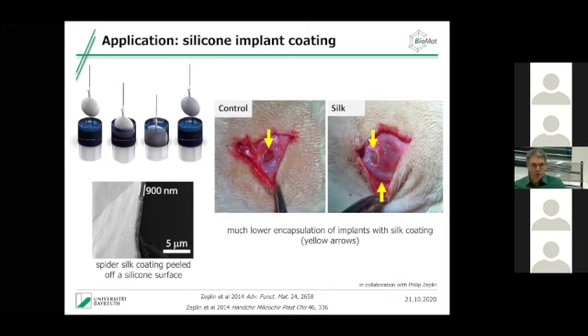And to make a long story short, well, first we tested that in vitro, then we tested it in vivo in rats. Now we actually went through the complete clinical trials with humans. And there are a lot of patients already in Europe running around with our implants. And therefore we now get the approval to get it freely on the market, and this will start soon. Here you see the benefit. So this is just a plain silicone implant, and this is the silk-coated implant. And you see a clear difference, even here in rats, that silicone surfaces are very attractive for human cells, and for rat cells in this case.